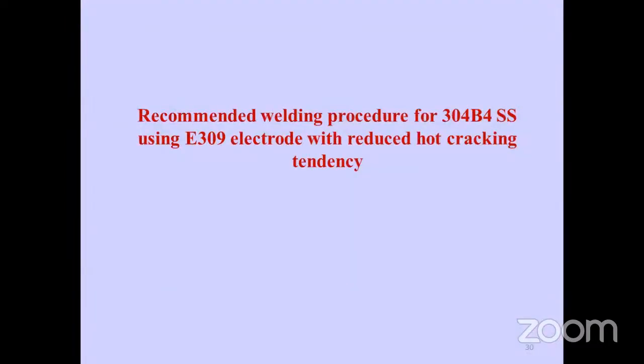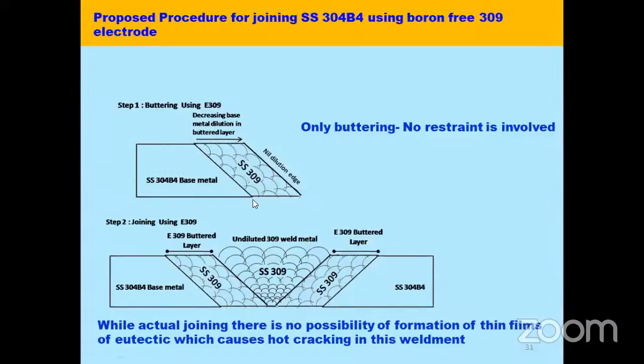So now we are going for a procedure modification to curb the hot cracking that is happening while welding using E309 electrode. Because we see that base metal dilution is playing a major role in increasing hot cracking susceptibility, we are using this 309 electrode to butter the surfaces that are to be joined. During buttering we have base metal dilution in the buttered layer, but we don't have any restraint because we are not joining it with any component. The restraint there is very minimal, though we have weld metal interdendritic liquid constituents present in this region. We don't have any restraint involved, so the cracking tendency is very low.